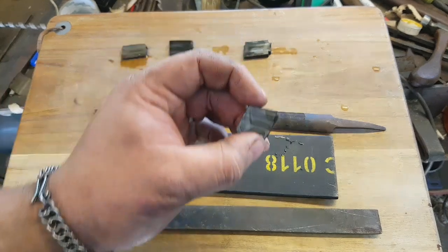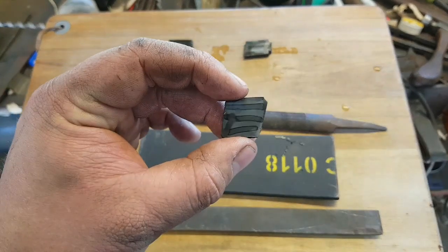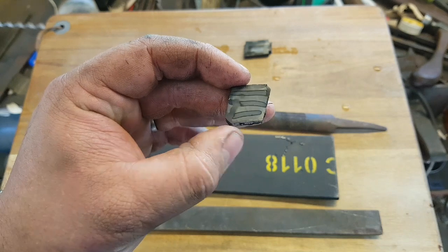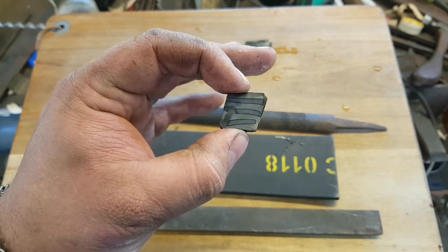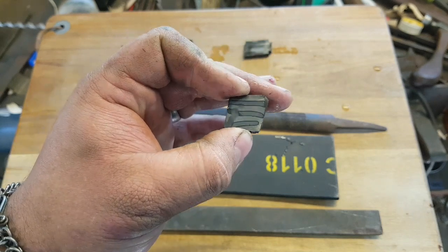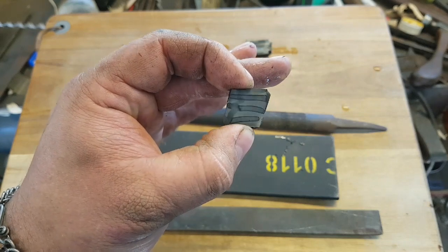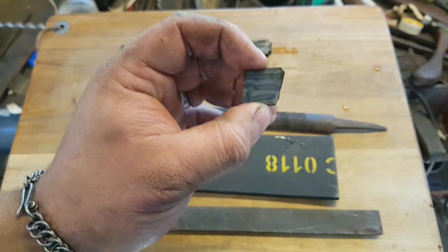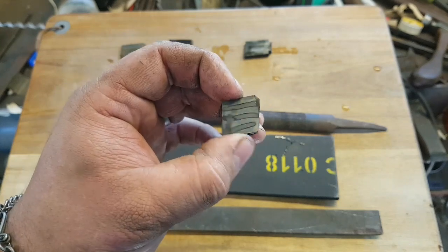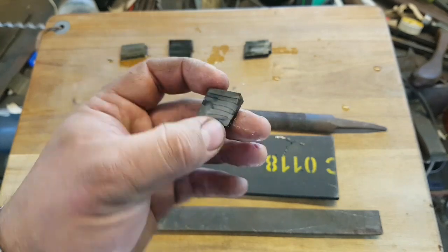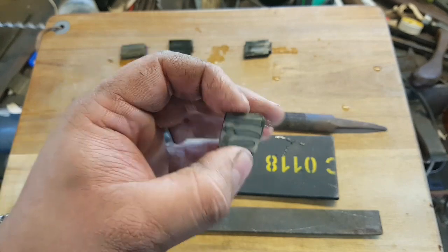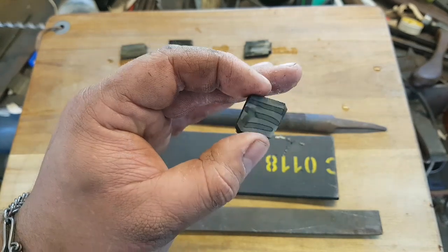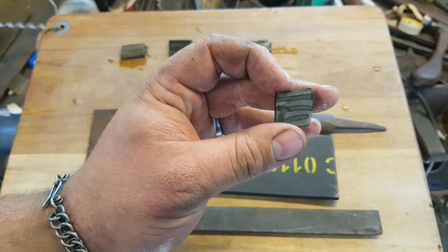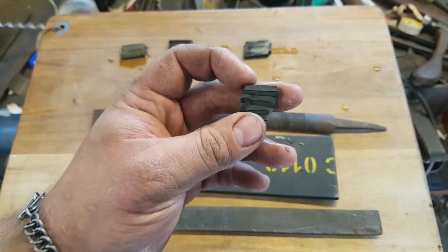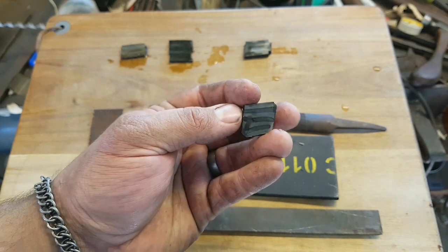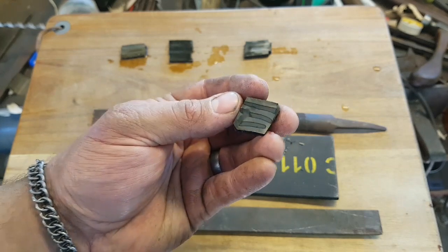Even more interesting is this little billet here. Bring it up to the camera because it's quite interesting. You can see the weld bead on this side here, but you'll notice that the file steel, which is the dark lines, has dark lines on the edges but is light in the center. That's because I used a Pakistani-made case-hardened file, and I was hoping that it would show something quite interesting, and it has. Now, this is the file steel and mild steel, so this was never meant to be a blade. The billet that this is made of is going to be a jacket over some 52100 bearing steel that we're eventually going to make into something. But you can see it makes a really interesting pattern.